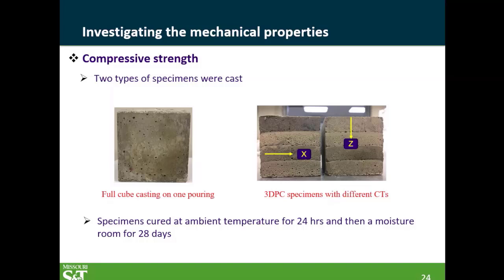So for mechanical properties, for each one of those mixtures, we made some concrete cubes. For each mixture, we have two types of specimens. One is a single cube, a monolithic one, and then we also have the layered one. For the layered one, we did tests in the X direction and then in the Z direction as well. For all the work that we did for the mechanical properties, it's ambient cure, so we didn't use any heat.